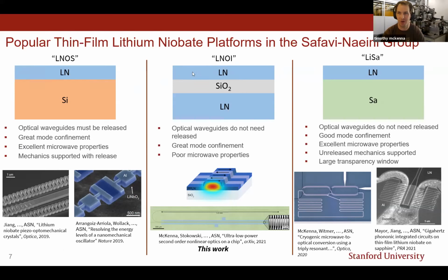Next, I'll move to LNOI. So this has a top thin film of lithium niobate on top of silicon dioxide. And you can make really nice waveguides, really good mode confinement, but not great microwave properties, especially if you're trying to make superconducting circuits, because one, you have some amorphous material here, and then it's not great to have a piezoelectric handle when you're making microwave circuits. But this is the platform that this work used.